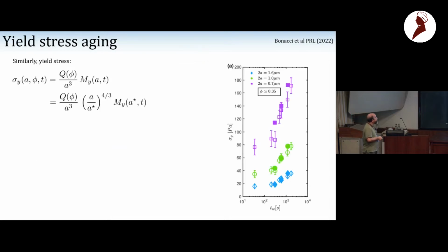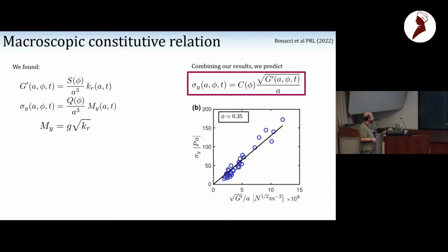Now, the point is that we can play a similar game. Expect that the yield stress is proportional to, is controlled by, the onset of rolling on the contact. Again, this seems to work quite well. So basically, the contact rolling limit will evolve with time and determines the evolution of the yield stress.